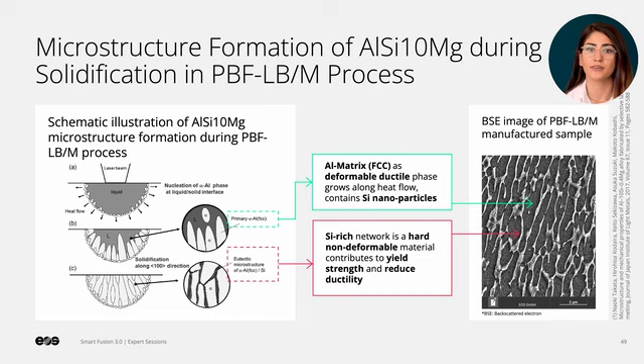Let's get back to our application parts to understand how Smart Fusion can help us to achieve homogeneous part properties like microstructural properties. We first need to understand how the microstructure of aluminum silicon 10 Mg forms during the laser powder bed fusion process. In laser powder bed fusion, as we know, a laser source selectively melts the material to create a melt pool. At the solid-liquid interface, the alpha aluminum phase begins to nucleate and grains grow in the direction of the thermal flow, which is normally perpendicular to the melt pool boundary.